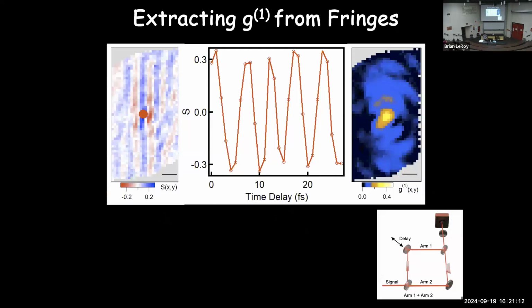And to really show that, what I can do is I can take this mirror and I can change the path length here. I'm basically delaying the time it takes on one path compared to the other. I'm changing the phase that the electrons accumulate there. So as I time delay this, these fringes will move. So if I look at this point here, it oscillates in time just because the path length is changing. And so by looking at how they oscillate, how strong they are, I can make a map of how coherent the sample is as a function of position.